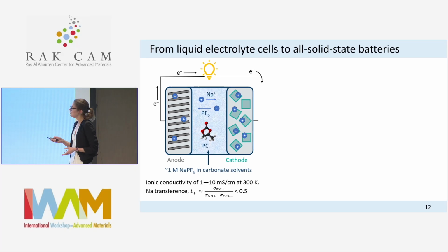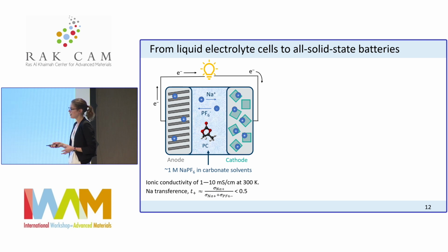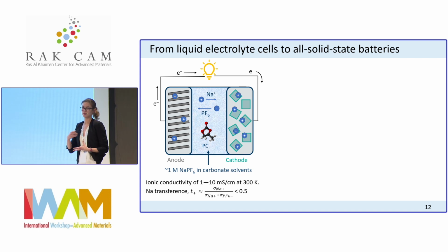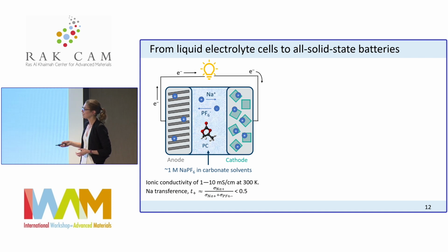The reason why we use such electrolytes is because they have a very high ionic conductivity, on the order of 1 to 10 millisiemens per centimeter at room temperature. But as you can notice here, when you dissolve your salts, you have this counterion that's also conducting as you apply an electric field. In fact, the sodium transference number, which is basically the amount of current that's carried by conduction of sodium ions, is less than 50%. So this transference number is less than 0.5.